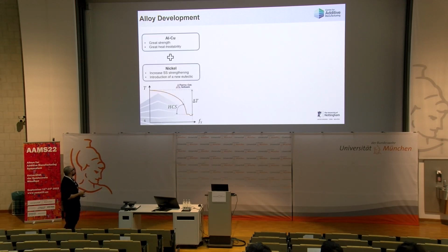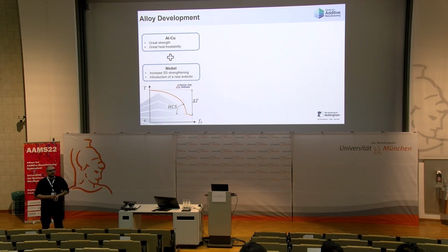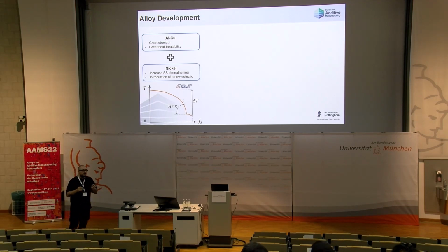Now we understand how to map these changes as a function of composition. But we also wanted to develop an alloy design and development process without powders. So first, of course, is the design of the compositions. We started with aluminium copper binary because it has great strength, great heat treatability, and is widely used in high-strength aluminum alloys. And then we added nickel as a third element in our ternary. This was for two reasons. One is to maintain a degree of mechanical properties, and the other is that, comparing the binary aluminium nickel and aluminium copper, aluminium nickel has a eutectic at a higher solidus temperature. This automatically, just by textbook, reduces the solidification range.